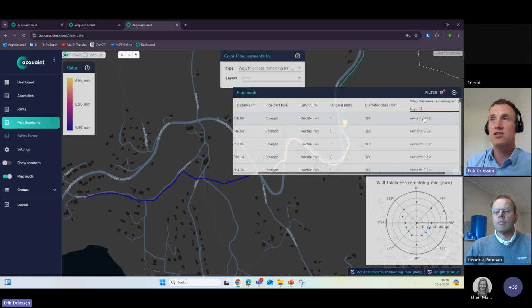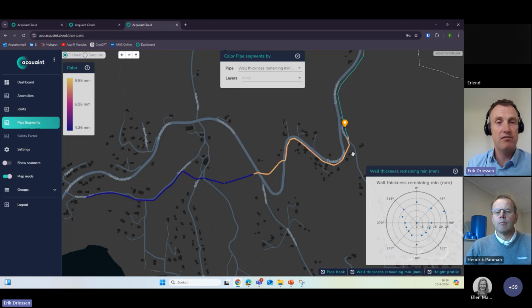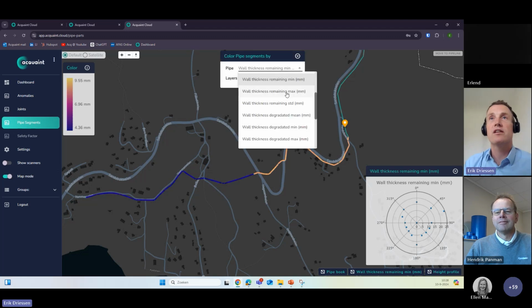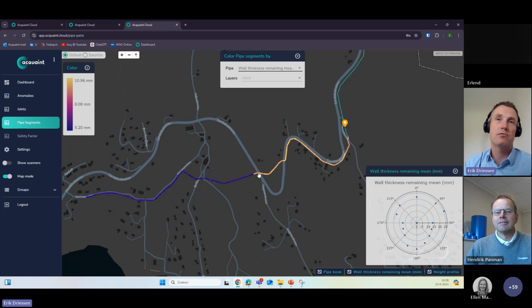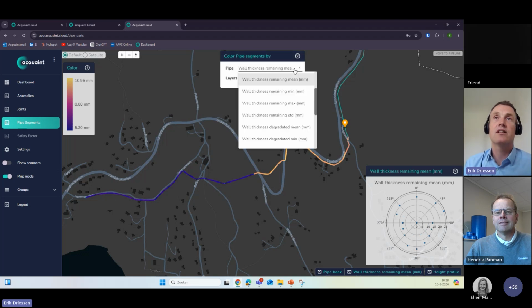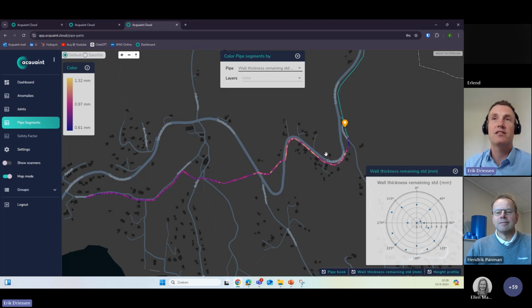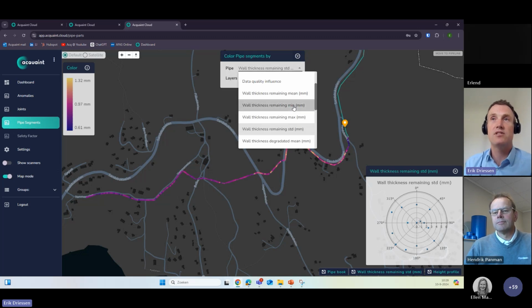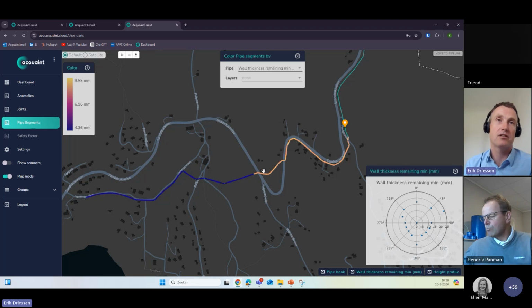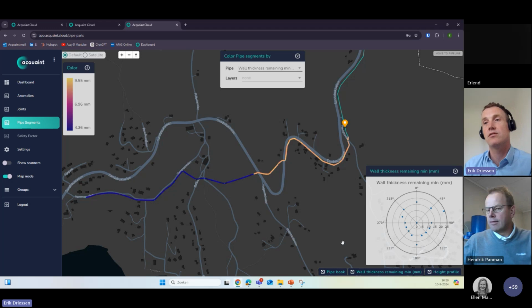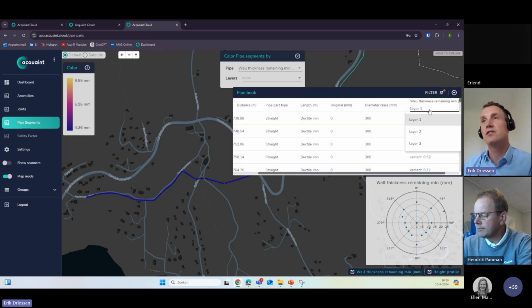So let me start with the first layer, that is a cement liner. And like Riens explained just now, in the graph we saw a big jump in wall thickness of the cement liner, which is clearly visible in this picture. You see here, the yellowish color is around 10 millimeters minimum wall thickness of the cement liner, and then it jumps down to around 5 millimeters. But when I select, for example, the mean, it's all very stable. It's a very stable wall thickness of the cement liner. You can also select the standard deviation, and that's also relatively stable. So again, like Riens also presented, it's an interesting observation that there seems to be a different type of pipeline, one with a thicker cement liner and one with a thinner one, but the cement liner itself was in perfect condition.